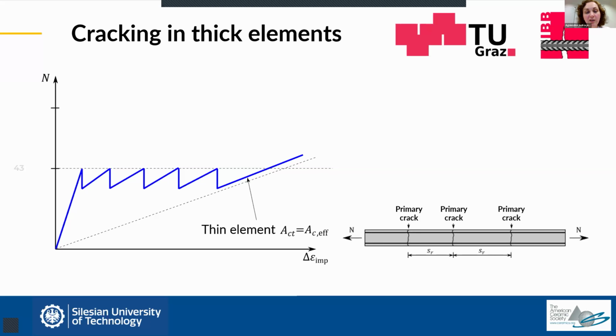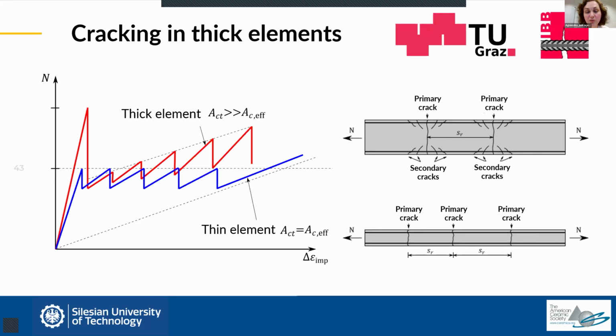When we take into consideration a typical tie, so actually a restrained element, we expect such a behavior. As the tie is being tensioned with an increasing value of force, it will cause the occurrence of subsequent cracks. Since this element is thin, these cracks will be through cracks and they will just appear one after another at the same level of force. The situation becomes complex when the element is thick and the reinforcement is located very close to the surface, which means it doesn't really affect the core of the element.